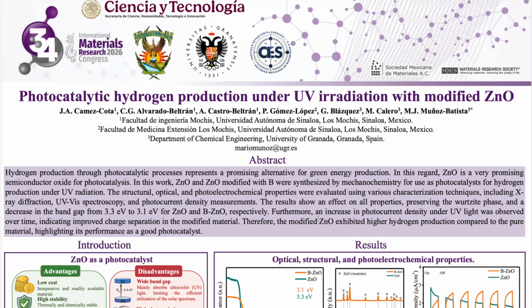Furthermore, an increase in photocurrent density under UV irradiation was observed over time, indicating improved charge separation in the modified material. As a result, the boron-modified ZnO exhibited higher hydrogen production than pure ZnO, demonstrating its excellent performance as a photocatalyst.